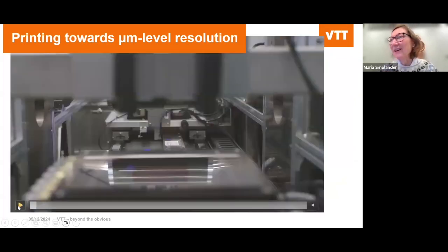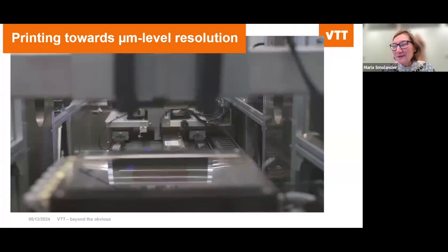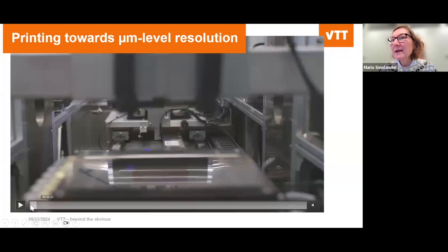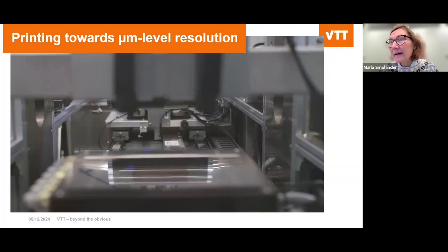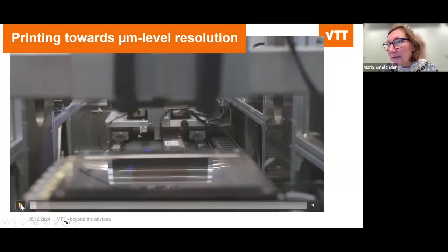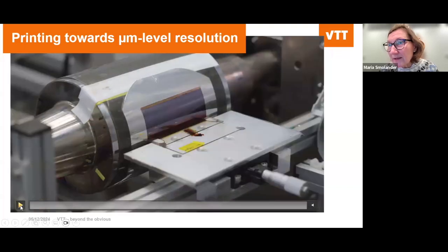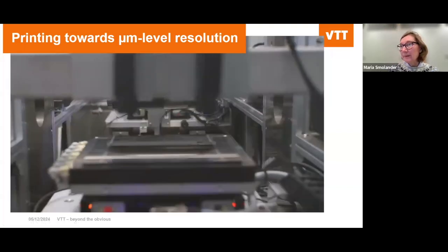Yes, and I will first explain a little bit because it's pretty fast. So what happens first is that the ink is applied on a PDMS blanket through capillary coating, and then this blanket is patterned with a kind of like the printing plate which has a negative image, and then the blanket has this semi-dry ink, and that is then further transferred to the substrates, which can be basically anything as it is smooth enough. And I will now show the video because it immediately starts with this ink application on the PDMS blanket.